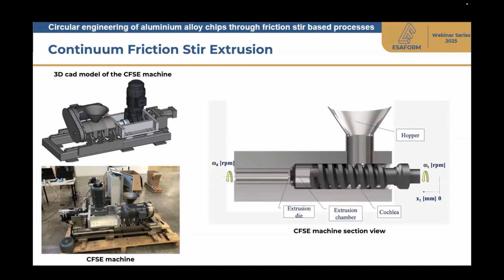Here you see both the actual experimental machine we designed first and then built, and the principle by which the process is carried out. Namely, the chips are placed in this hopper, and they are conveyed up to such a cochlea, which is put into rotation and starts to heat them just by friction, moving all along the fillet of the cochlea. And the chips are then pressed against an extrusion chamber in which a tool, an extrusion die, is found and put in rotation with another engine of the machine.